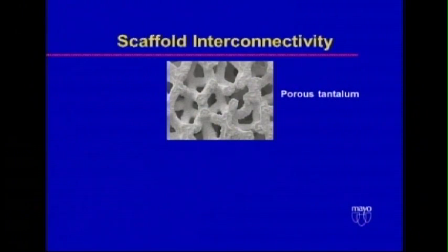Now, how about interconnectivity? One of the issues when we make these scaffolds is we want tissue to grow into the pore spaces, and are they interconnected? I would submit to you that those scaffolds that Kiwan just made, that I showed on the last slide, they're interconnected. But we use a couple of other ways of making porosity. We use porogen leaching, we use gas foaming, and we've tried all of these over the years. Each of them has pluses and minuses. The porogen leaching, sometimes there's a bunch of big holes where the salt particles that we use for the porogen bunched up. Sometimes there's holes that aren't connected to anything else if the salt particle was by itself. Same problem with gas foaming. We put something in that during the reaction will make some CO2, and sometimes we got big bubbles, sometimes we got little bubbles.